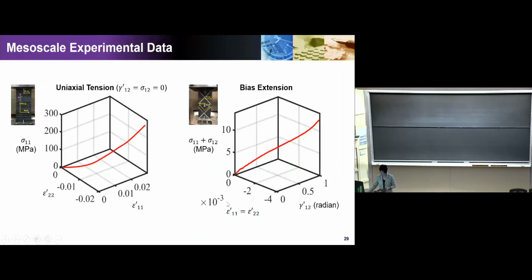The data we used in calibration only involves data from the uniaxial tension test. That means your shear angle is 0. Basically, you pull the specimen in one particular direction, and you look at how the stress sigma 11 changes as a function of different strain levels. So that is a curve that you record.